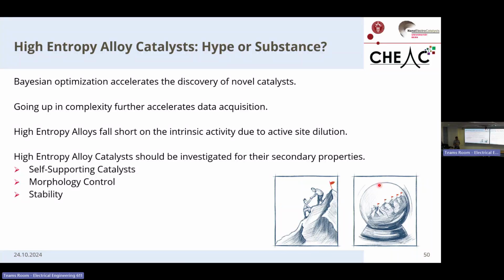This could be looking into aspects such as the self-supporting property of a catalyst. So your support becomes a part of the matrix of your catalyst. You can look into the morphology control. So you add elements that are going to leach out specifically, creating a specific morphology that is highly active. And of course, we can look into the stability, on how stable is a high entropy alloy catalyst, because that's a completely unknown question.